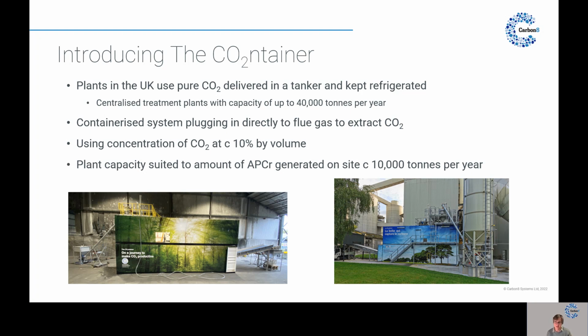And we undertook a trial in Ontario, funded by the Ontario Centre of Excellence, and demonstrated that this was possible using concentrations of CO2 at something above 10% by volume in these typical flue gases from either cement works or an energy from waste plant.